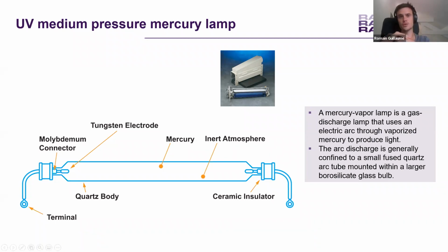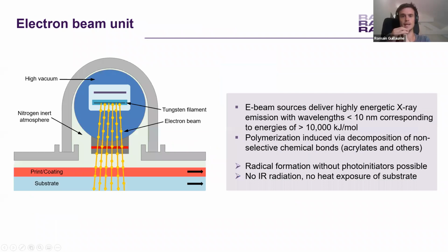Then we have the electron beam unit. So the electron beam sources deliver highly energetic X-ray emission. So the wavelength is below 10 nanometers. When we have a mercury lamp, we have wavelengths between 200 nanometers and let's say 500 nanometers. So here we have very, very low nanometer wavelengths with high energy.